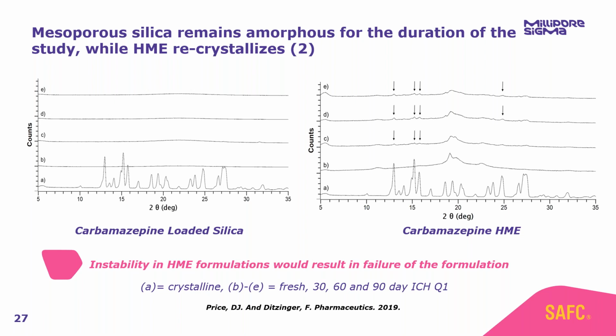Carbamazepine simply is not stable in this hot melt extrusion formulation, and so over time in these accelerated conditions, we get recrystallization of our formulation. So both hot melt extrusion formulations, carbamazepine and haloperidol, would have failed the regulatory requirements for stability. And there's a good reason why these requirements are in place.